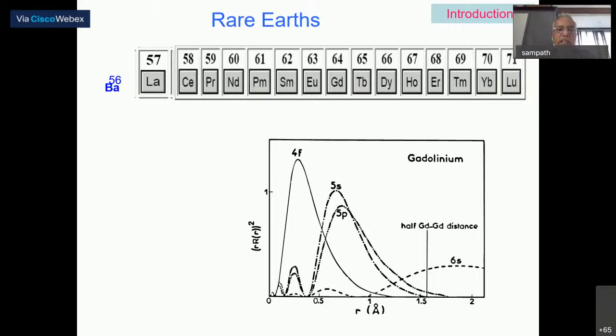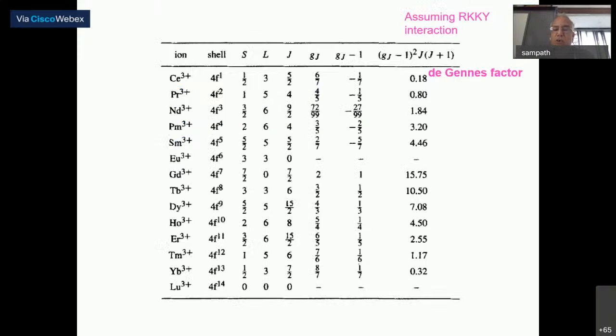Okay, so given that 4f electrons are strictly localized, there is a very famous factor called the de Gennes factor. We call it (g_J − 1)² J(J+1), where g is the Landé factor and J is the total angular momentum. You can derive a parameter called the de Gennes factor. It is expected that many of the properties, like magnetic ordering temperature or spin disorder resistivity, scale with this factor. If you know the number for one, you can predict what the number should be for the other. This often breaks down at the beginning of the rare earth series because, as I already mentioned, there is some degree of 4f electron delocalization. So kindly remember this particular factor in my talk.